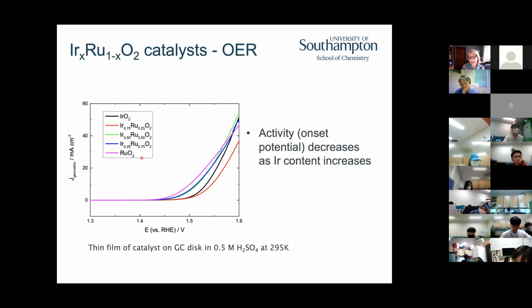If we look at the activity of the materials, most people do rotating disc experiments where you take a thin film, catalyst film, on your rotating disc. So by dropping the ink on the catalyst, you can see that the ruthenium has the lowest onset potential for the oxygen evolution reaction, and iridium is over here. The mixed materials are in between, right? Don't think about the currents over here, because in these rotating disc experiments, these currents over here are really dominated by resistance. So you really need to think about where the thermodynamic part of the kinetics is affected.